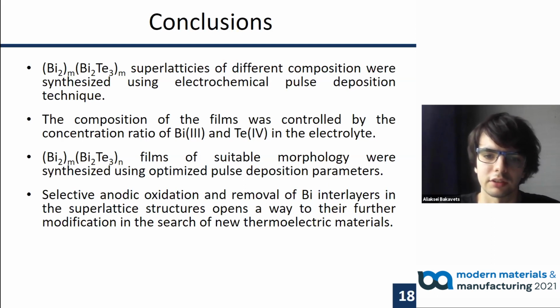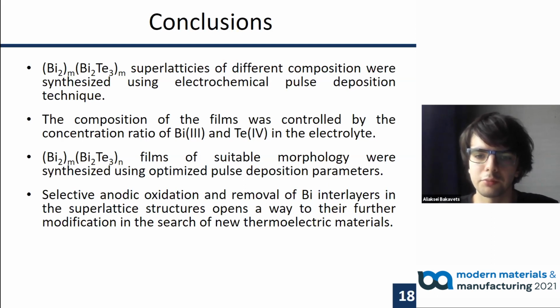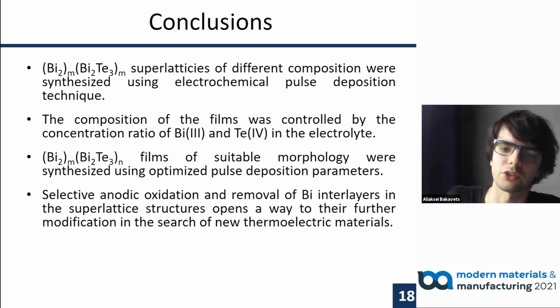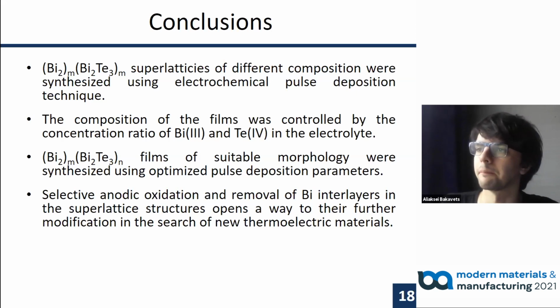Additionally, we found out that selective anodic oxidation of bismuth bilayers and their removal from the superlattices is possible and results in expanded Bi2Te3 structure, which is of interest for introduction of other elements.